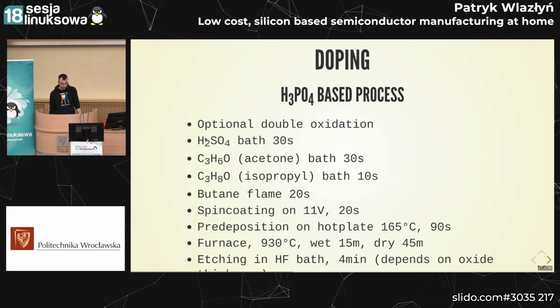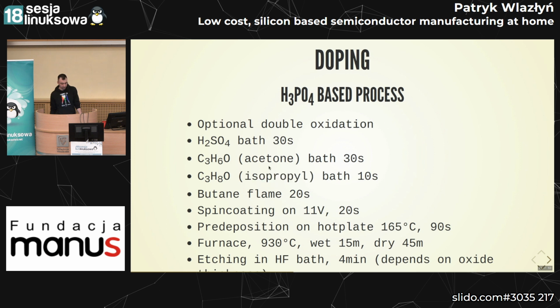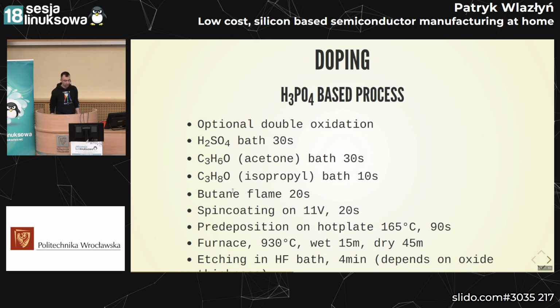Now, the doping process also involves some cleaning, and we use sulfuric acid for it. First we begin with the sulfuric acid bath. It will remove all the organic residue. Then we do an acetone bath and an isopropyl bath that will remove the acetone residues. When we have a cleaned wafer like this, we put it on a butane flame for around 20 seconds. Then we put it on the spin coater with the phosphoric acid solution I was mentioning on the previous slide. We spin it by supplying 11 volts to the computer fan for 20 seconds. And then we put it on a hot plate for pre-deposition.